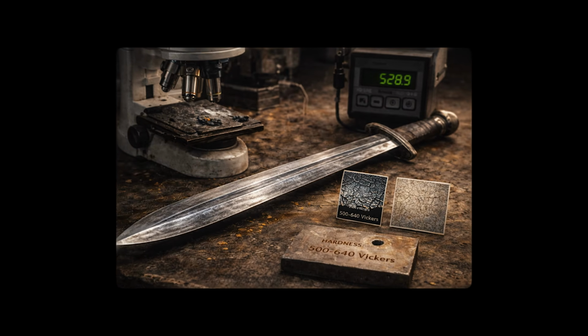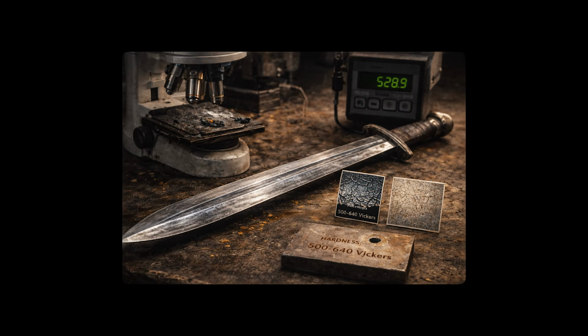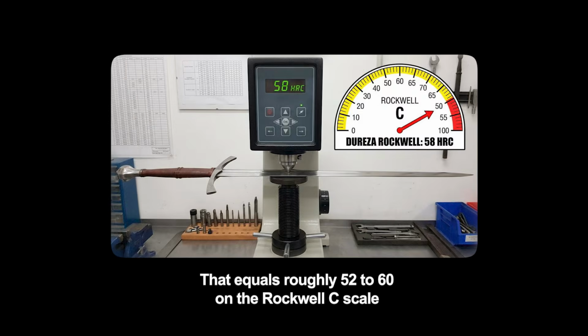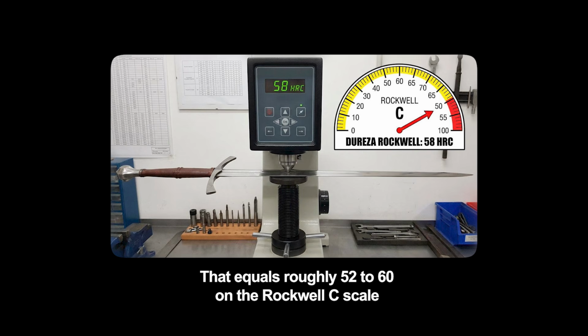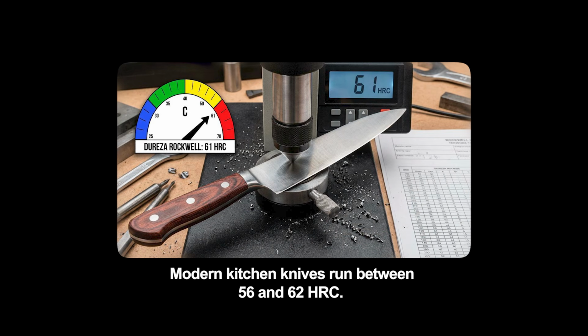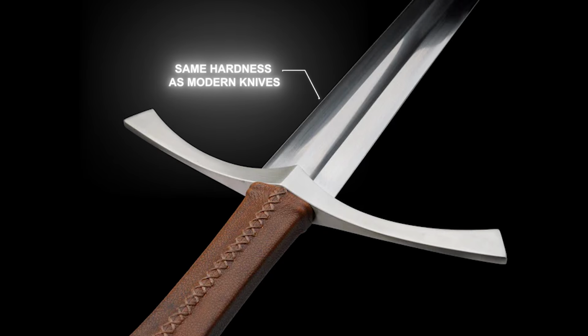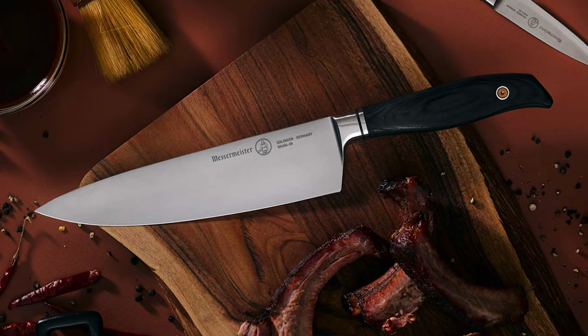To put that in terms that matter, 500 to 640 Vickers is roughly 52 to 60 on the Rockwell C scale. Modern kitchen knives run between 56 and 62 HRC. That medieval sword's edge was sitting in the same hardness range as contemporary professional cutlery, not close to it, in the same range.